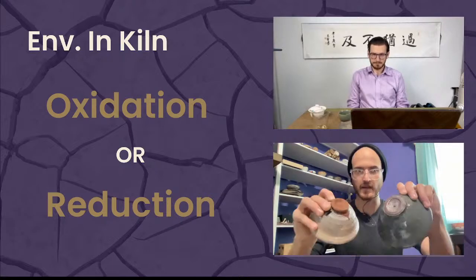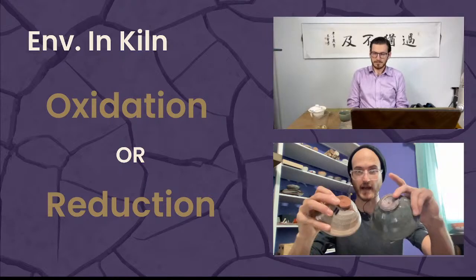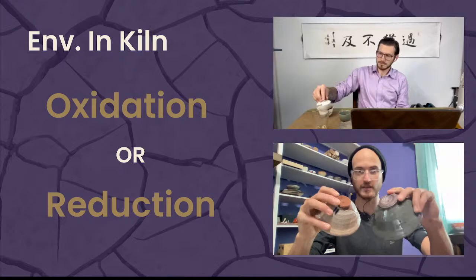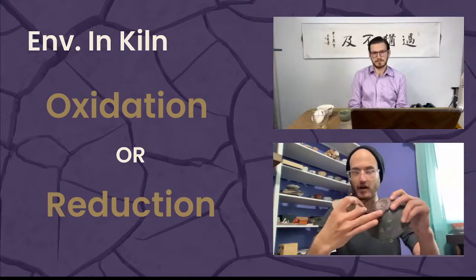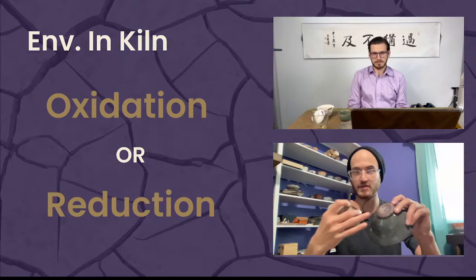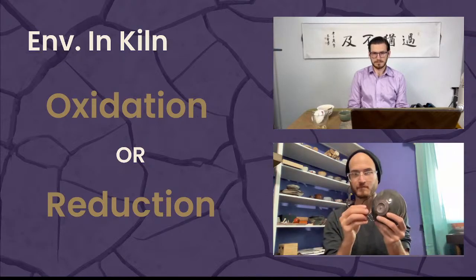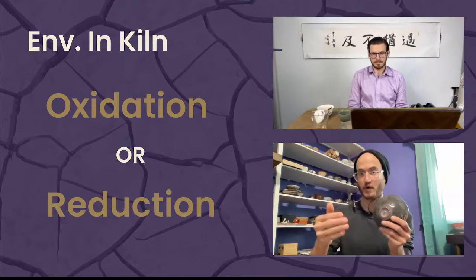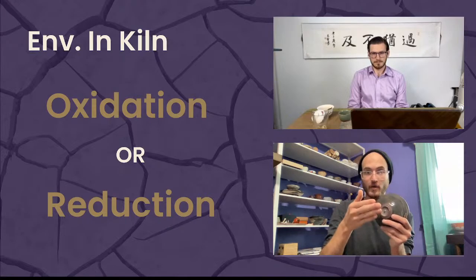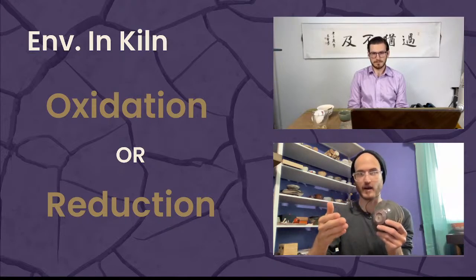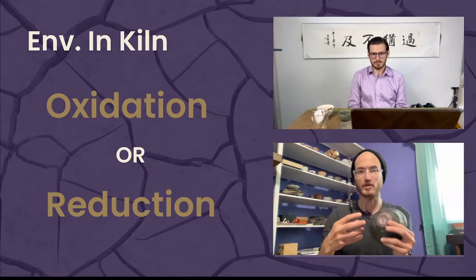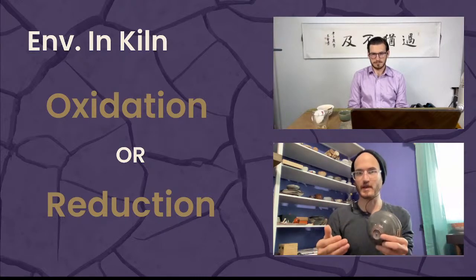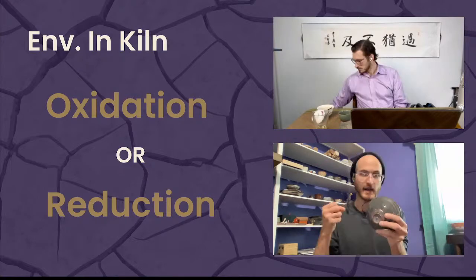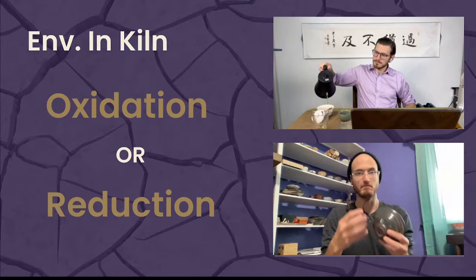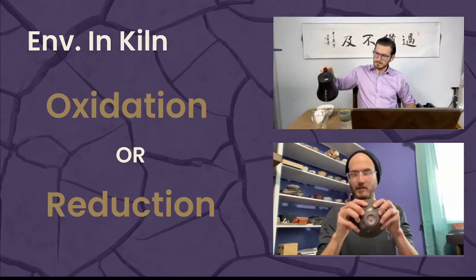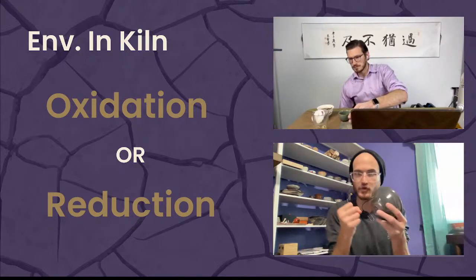This is my Lizella, and it's a very highly iron bearing clay. So what happens is that all of the iron in the clay is interacting actively with the atmosphere, and you get a really big color change, and it's a texture change as well as a density change. So each iron molecule is turning from Fe2O3, all of its oxygen is getting stolen away, and it's becoming FeO, just ferrous oxide. And that's much, much stronger of a melter than Fe2O3 is. So the effect is that it pulls away that oxygen and it makes the clay and the glaze melt much more. So all of the particles of iron stick to the particles around them, and it glues and gels together the whole structure of the clay.